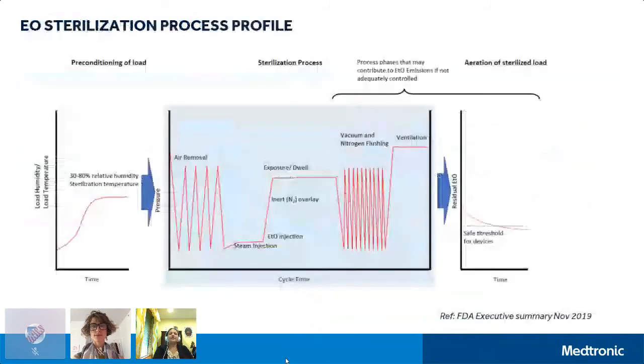One of the things I would like to point out here is a typical sterilization process profile that describes the mechanism of how EO works. The first step is the preconditioning phase, where you require the load to be brought up to a specific temperature and humidity level. And these are very essential for proper sterilization. The important thing to note here is the humidity requirements. A 30 to 80% humidity range is preferred for optimum sterilization effectiveness.